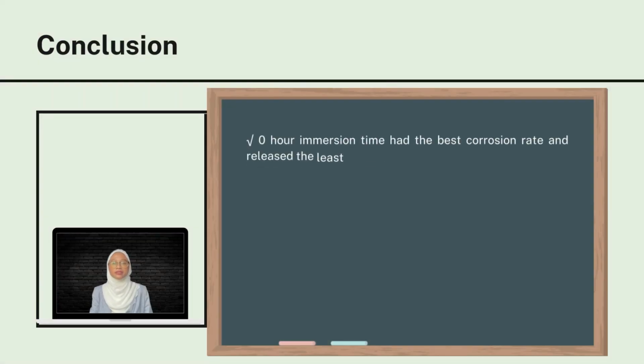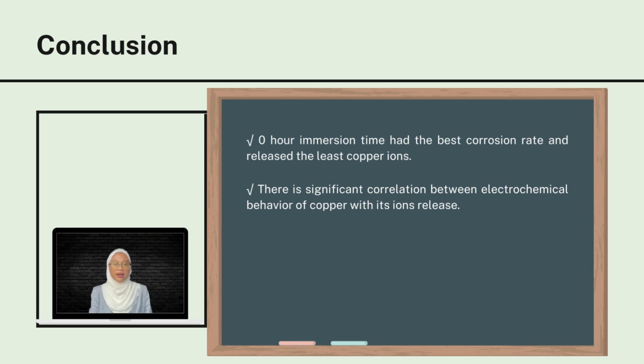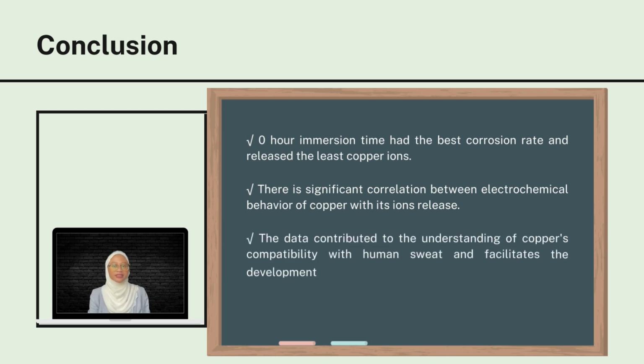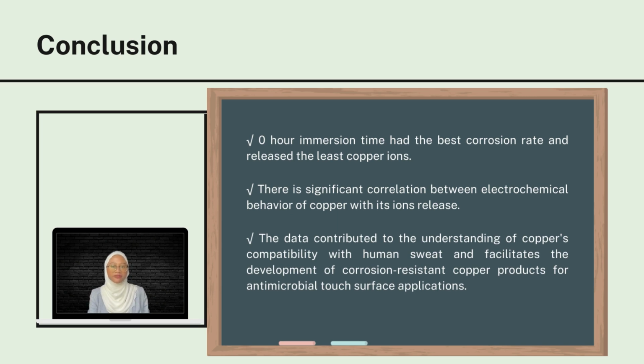In conclusion, 0 hour immersion time of copper in the artificial sweat solution showed the best corrosion rate with 0.09412 mm per year, which also released the least copper ions with 0.128 mg per liter. At last, the third objective had been determined: corrosion resistance of copper significantly correlates to copper ion release, by which the longer its immersion time in the artificial sweat solution, the less resistant it is, as it releases more ions. Certainly, the data of this study may contribute to the understanding of copper's compatibility with human sweat and facilitate the development of corrosion-resistant products for antimicrobial touch surface applications.